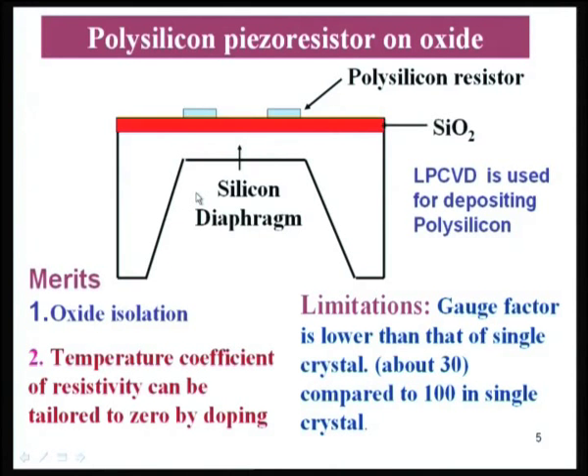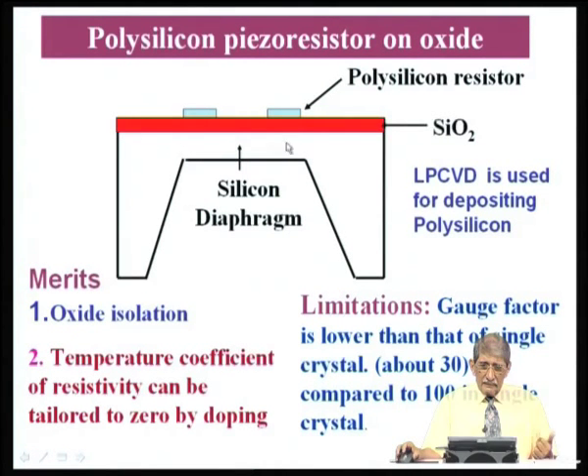So, the way you do this polycrystalline resistor is like this. Take a silicon substrate, use bulk micromachining technique to etch the silicon from here, this is a cross section, so that you get a membrane whose thickness is decided by your etching. 10 micron or 15 micron will be the thickness of this membrane, and the dimensions are also decided, as we discussed yesterday, by the pressure range that you want to use it. Okay. Now, I grow oxide on that, and on the oxide you realize polysilicon resistor.